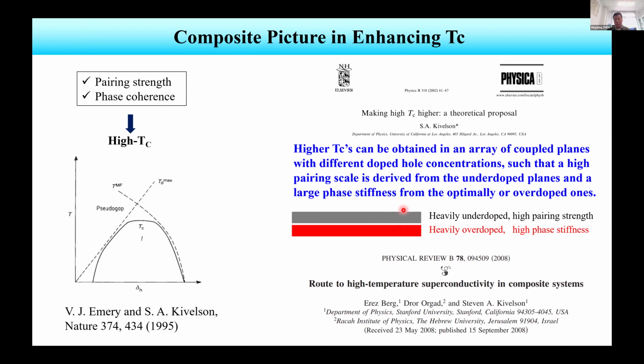things. If we have two layers, one layer is heavily underdoped, but it has a larger gap. That means it has higher pairing strength. The other layer is heavily overdoped. That means it has high phase stiffness, a higher coherence temperature. Then we put the two together, and if there's some interaction between them, we can realize higher TC. So this is the so-called composite picture proposed by Kivelson and others some years ago.